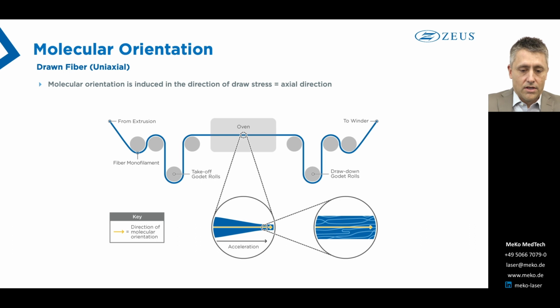So if you take a look at that first inset that shows the cone there, what's happening there is as the fiber comes into the oven as shown at different speeds, so it comes in at one speed and it exits at a faster speed, you get an acceleration. And that acceleration has a deformation to it, and then there's a resistance to that deformation which causes stress. And that uniaxial stress ultimately causes uniaxial orientation. And also what can happen there is you get some strain-induced crystallization, which we won't go too much into, but just know that also happens when we orient our tubing.